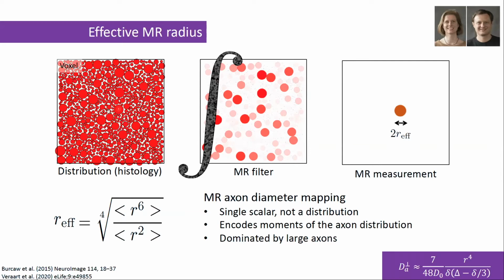The larger axons have most likely more protons, so they weigh in more strongly in a diffusion-weighted signal. In the previous equation, I showed that there's a relationship between the apparent diffusion coefficient and R to the fourth, and that adds to the dominance of large axons in our signal. And now, of course, we are not measuring the distribution. We have to integrate all the axons within our voxel, so we get one single number, which is what we call the effective radius. And that number represents the entire distribution that is dominated by the large axons.